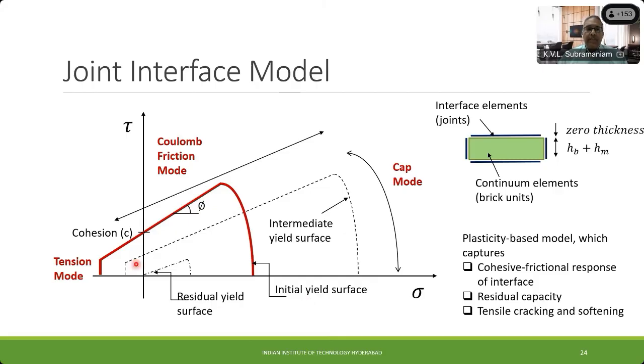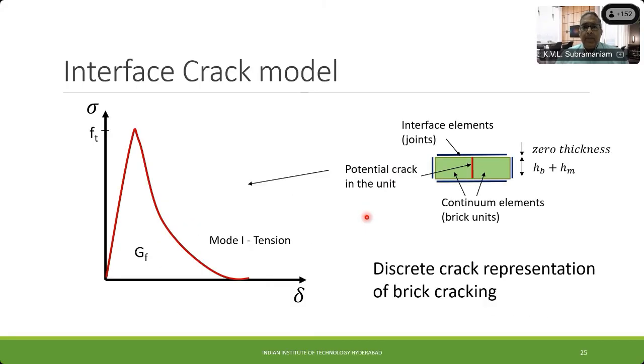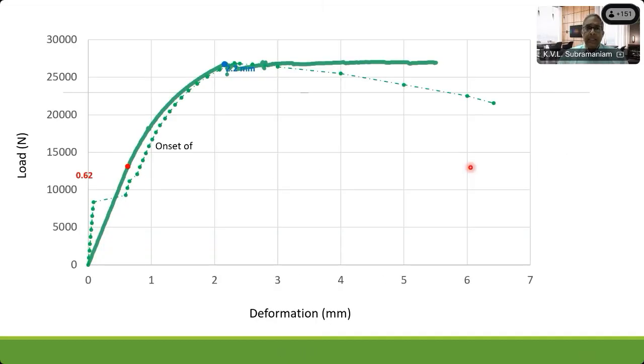Basically, we model the interface as a Mohr-Coulomb frictional type of a material with a tension cutoff and a compression cap. And all of these parameters that you need for the model can be obtained from the shear test that we perform. And when it comes to the head joints, we can basically put a vertical gap between the two brick elements where we expect to see splitting between the bricks.